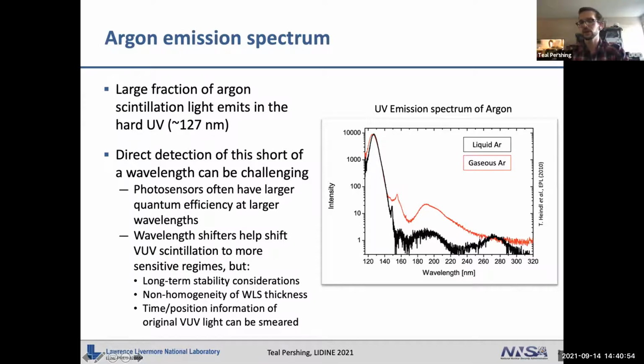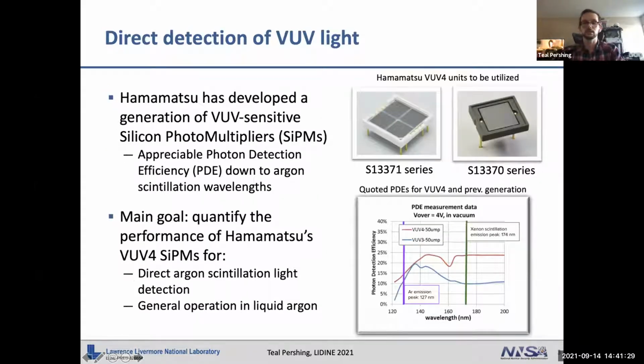A lot of commercial photosensors don't have the quantum efficiency at these short wavelengths. They're at longer wavelengths, so you generally use wavelength shifters to shift this UV light to more sensitive regimes for these photosensors. But as we've seen today, there are other considerations: long-term stability, how you've actually deposited the wavelength shifter, any non-homogeneity concerns, and you can also lose some time and position information from the absorption and re-emission. If those are concerns for you, it would be great to directly detect your scintillation light and not have to worry about wavelength shifters.